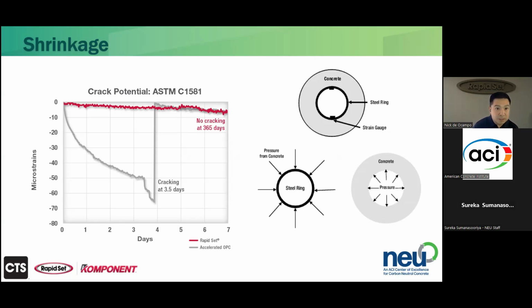If you look at the rapid set ring, we only get less than 10 microstrains for the rapid set material, and because it never builds up enough pressure, it doesn't crack. It's still less than 10 microstrains at 7 days, and we've had multiple specimens in these ring tests for over 365 days, and so long as the shrinkage remains less than 10 or 20 microstrains, that material does not crack.